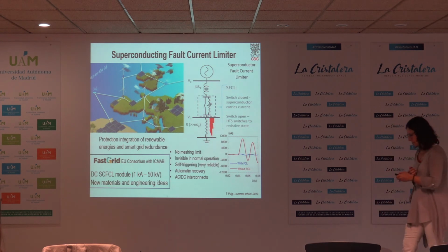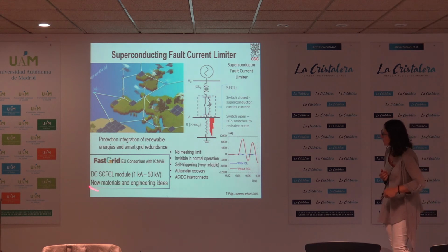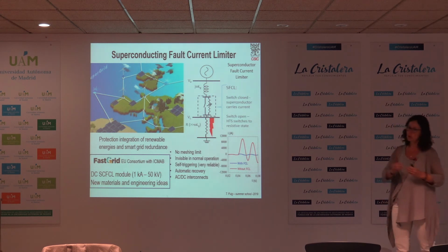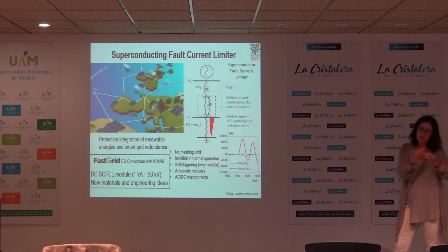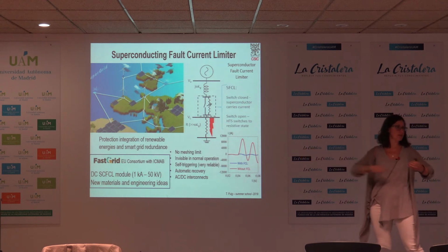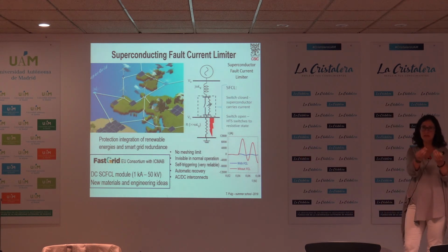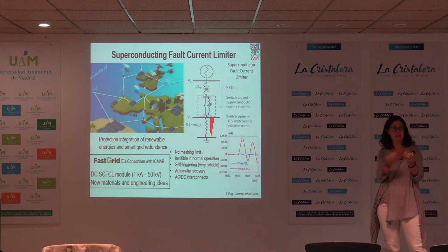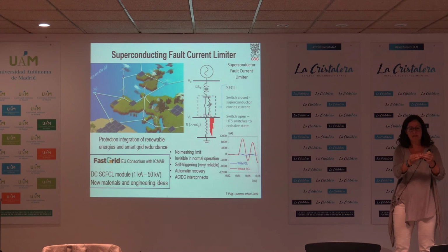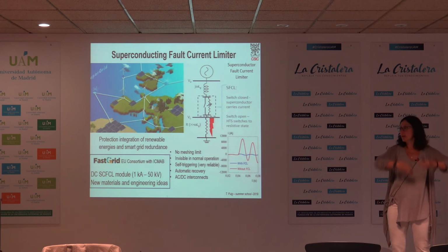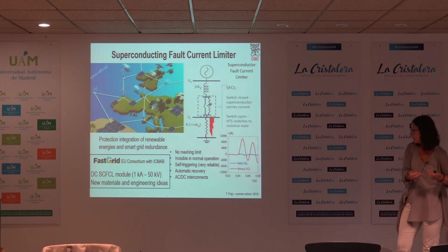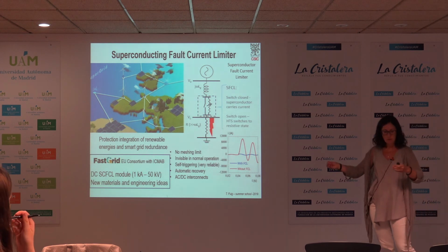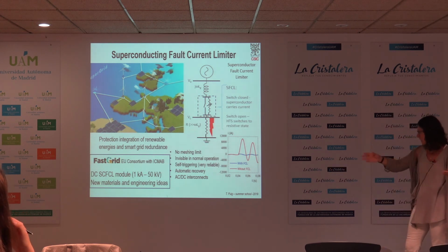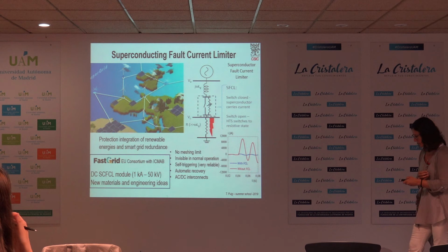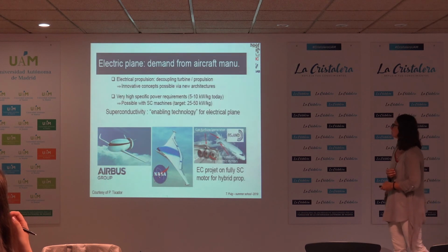And here, the main issue in the fault current limiter is to quench the material in a homogeneous way. Because as I said, when you quench this material, the thermal conductivity of HTS is very small, and therefore you quench here but you don't propagate, and therefore you can really break the material. However, there are means to make this quench propagation much faster, and these are the ideas and materials in this project.